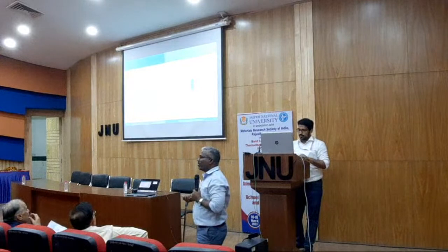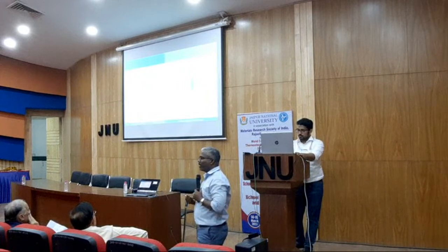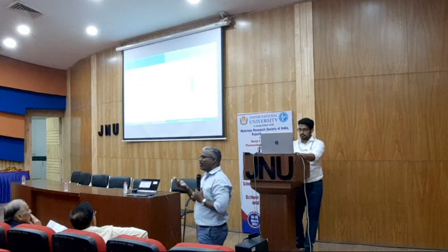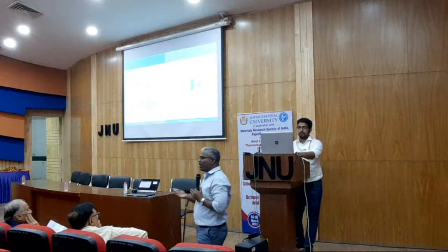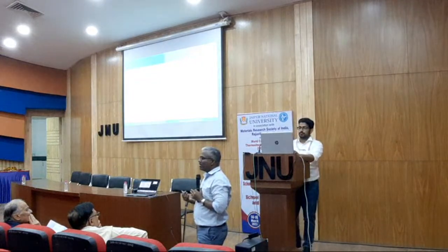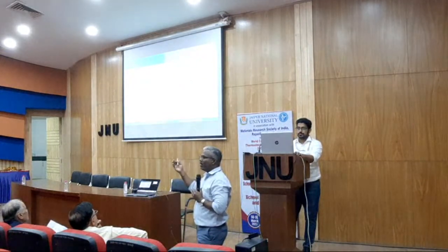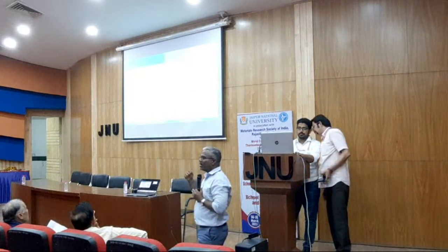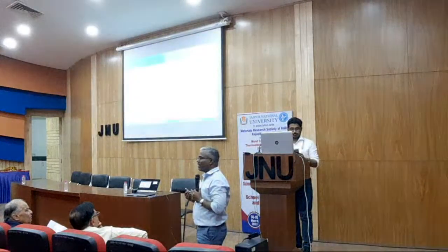But the Seebeck effect was discovered 200 years ago. Only a few months back people celebrated 200 years of the Seebeck effect. Still, it's not commercial, though the Seebeck effect is much older than photovoltaics, and it has not come into application. The reason is that people are working on bulk materials, majorly for high-temperature applications. The problem with high temperature is that once we heat one end, we need to maintain the delta T. But with a bulk material, the other end can also absorb heat, so the delta T cannot be increased or maintained properly. Because of that, bulk materials have not been much used in industry applications.